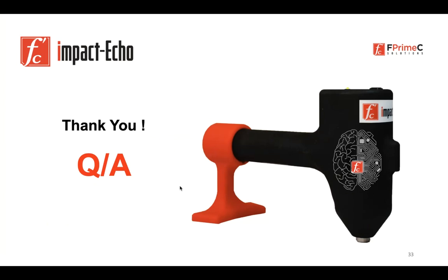Of course, with frost on the surface, when the temperature goes a lot down, the stiffness of the concrete increases a lot. Even in poor concrete, because of the low temperature, we expect to overestimate the stiffness of concrete because of the frost. I don't recommend using Impact Echo or any other NDTs for a temperature less than minus one or two, minus five really.